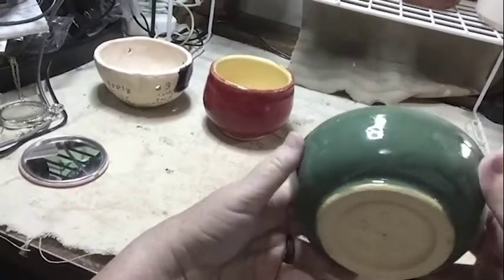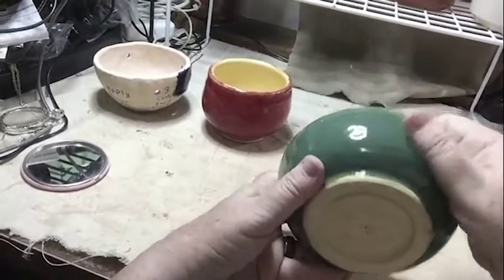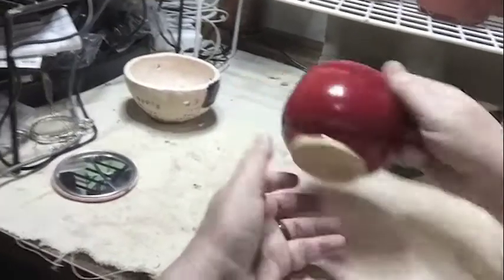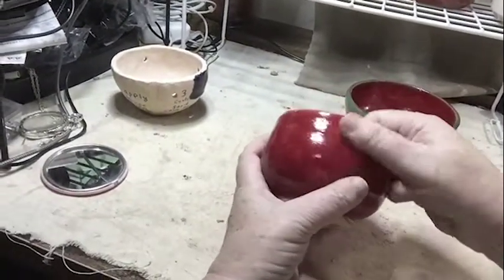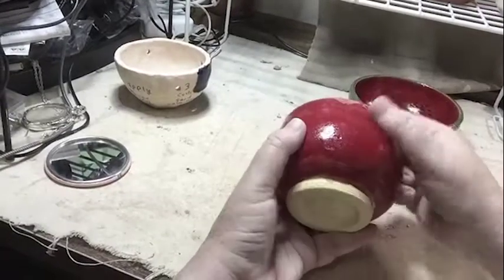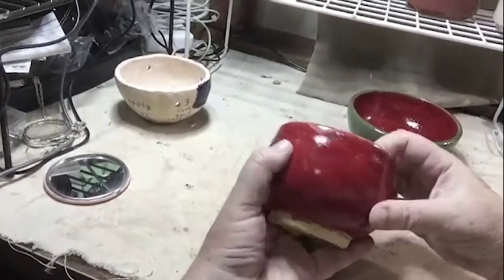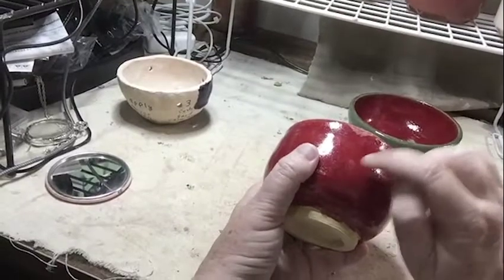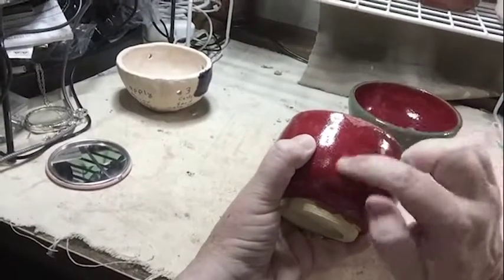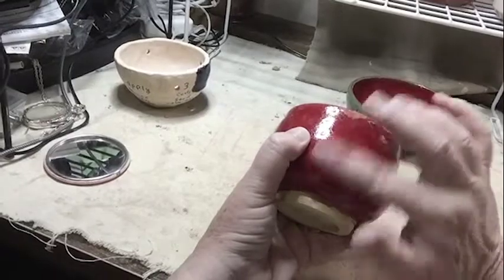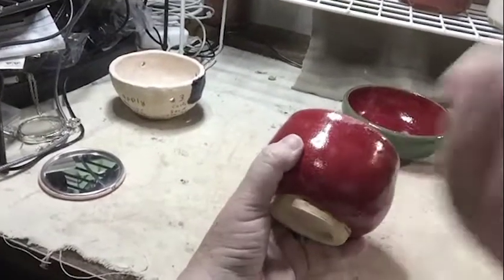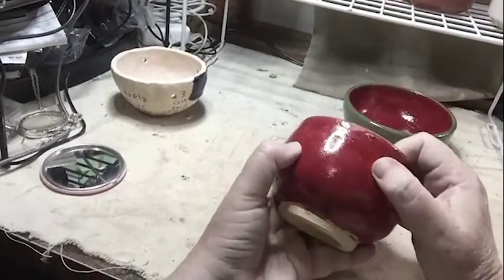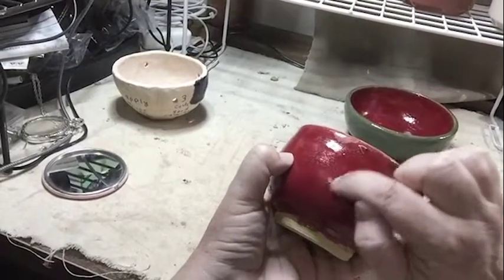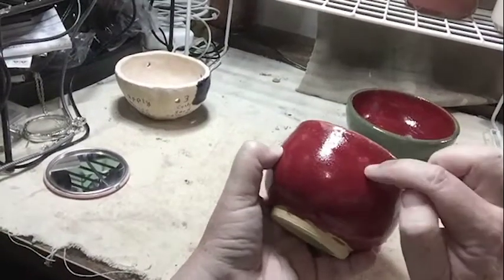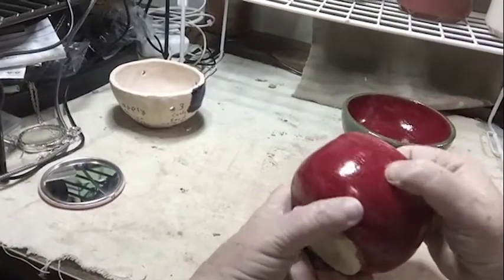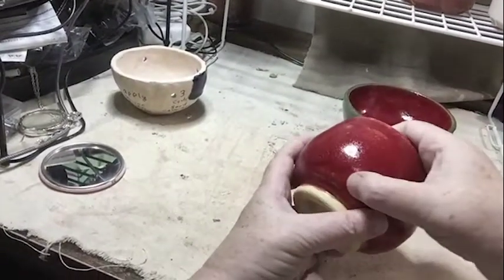Okay, so another thing that could happen is if you apply too thickly and you also don't allow your coats of glaze to dry in between application, what can happen is that the brush will lift off pieces of the coat of glaze that you've got underneath. So say you put on your first coat, it's just barely dry, you rush to put on your second coat, that can lift away the glaze that's underneath here, and you can see I've got these little bald patches that are happening over the surface of this. Okay,